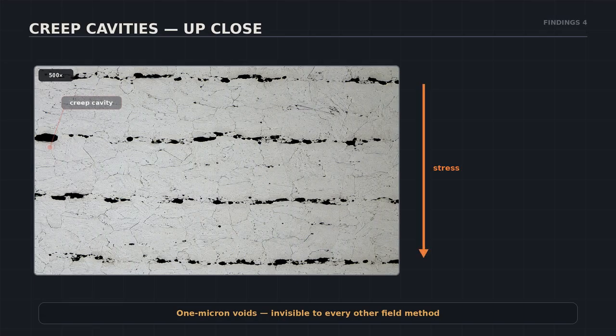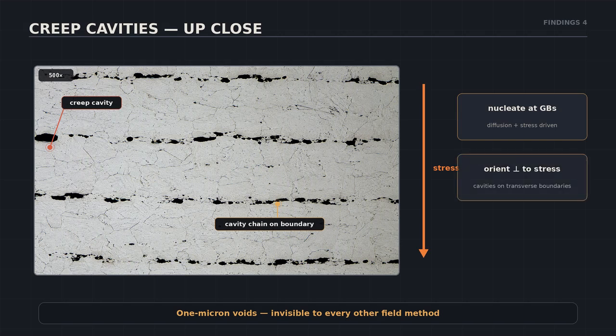Look closer. Each dark dot is a cavity, roughly a micron across, sitting exactly on a grain boundary. They nucleate where diffusion and stress combine, and they orient perpendicular to the loading direction, which is why experienced inspectors can tell you the stress state from the cavity pattern. Small as they are, these voids are the earliest warning you will ever get.